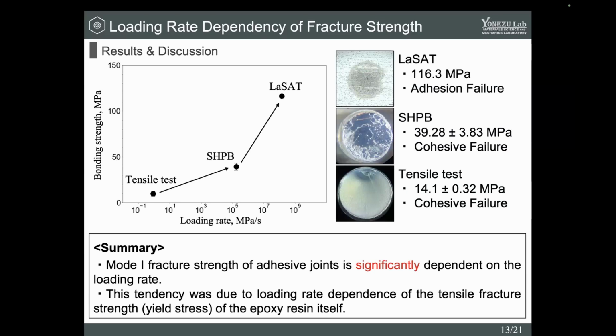Compared with SHPB test and tensile test, fracture morphologies were same. It indicates that the tensile strength of epoxy resin increases as loading rate increases. On the other hand, compared with LaSAT and SHPB tests, fracture morphologies were different.